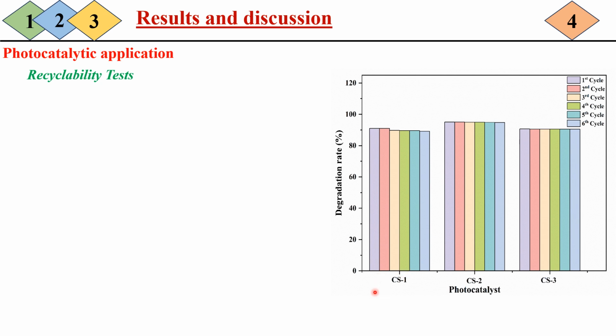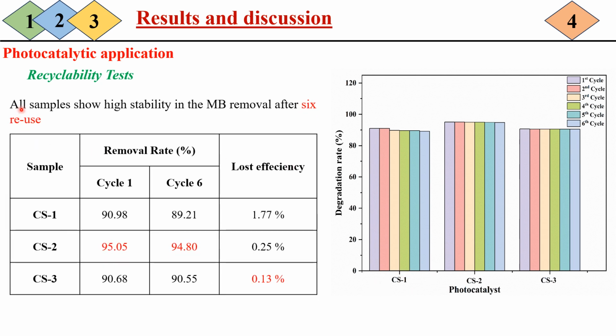So, for the recyclability test, we used the same procedure for all samples. As we can see, all samples show a high stability in the MB removal. The loss of efficiency was 1.77% from cycle 1 to cycle number 6 for sample number 1. For sample number 2, which is the best photocatalyst, we lost only 0.25%, and for the last photocatalyst we lost only 0.13%. As a result of this study, our prepared photocatalysts are efficient and stable.